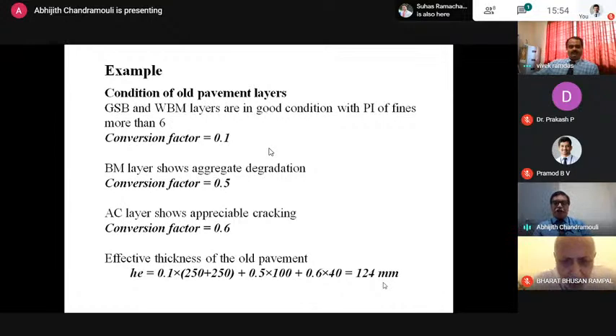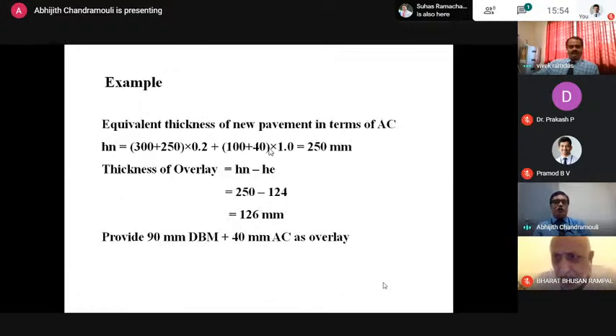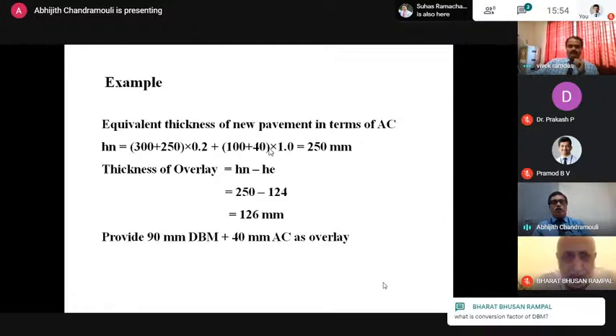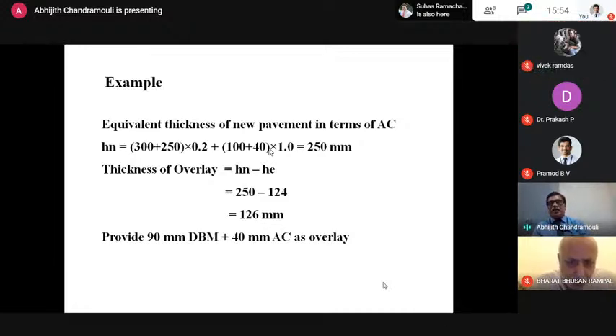Getting into the new pavement, the equivalent thickness of the new pavement in terms of asphalt concrete or bituminous concrete: HN is equal to 300 plus 250 into 0.2, and so on, a calculation similar to H1 C1 plus H2 C2. If I do that, I get a thickness of 250 millimeters. So this 250 millimeters of bituminous concrete or asphalt concrete has to be provided.